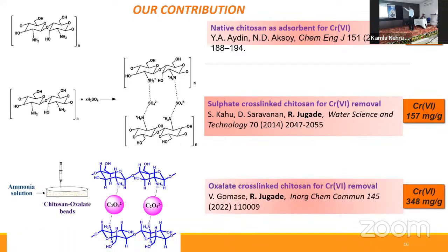Further, we carried out one more type of cross-linking by using a simple oxalic acid. Again, the adsorption capacity for chromium was improved to 348 milligrams per gram.